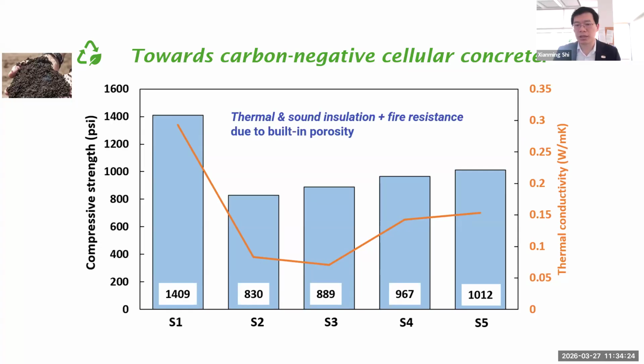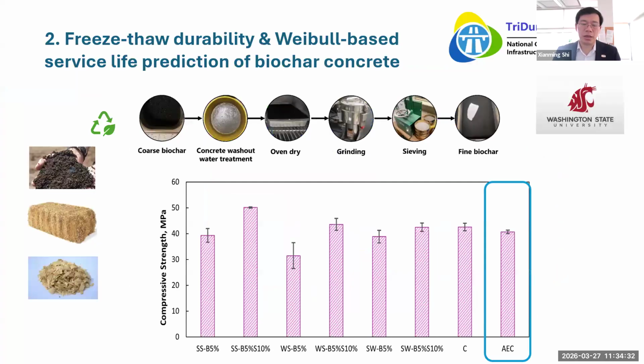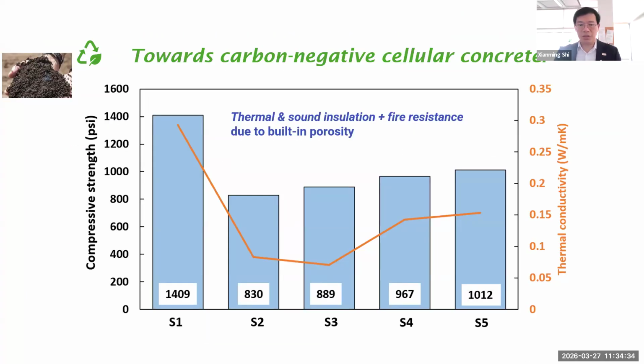So you look at the thermal conductivity, they're actually well within a range designed or specified for this type of cellular concrete. Well, that's the first study. So we show that biochar has great potential, and despite a conventional wisdom of not putting carbon-rich material into concrete, we did it anyway, and it works out. And the key, though, is we need to understand what type of biochar and what type of microstructure or surface chemistry.